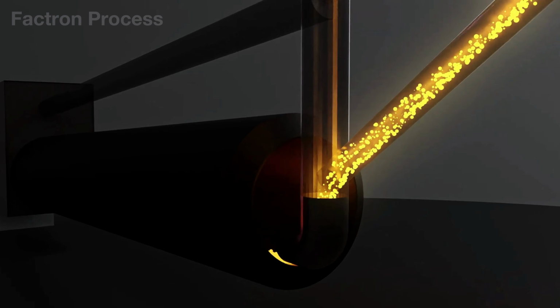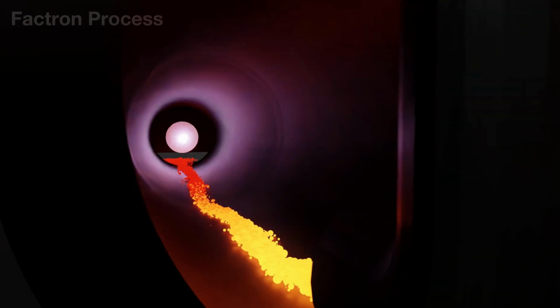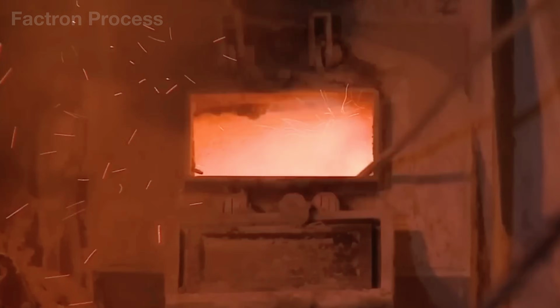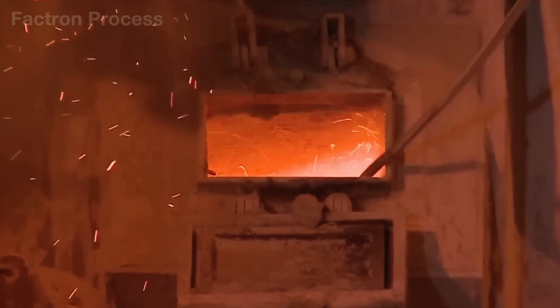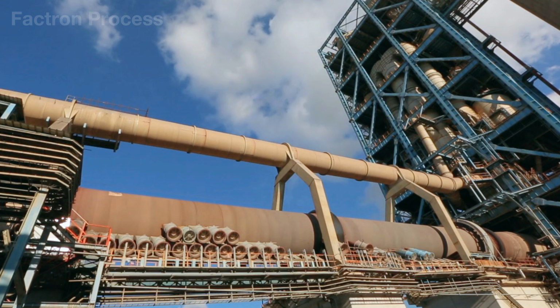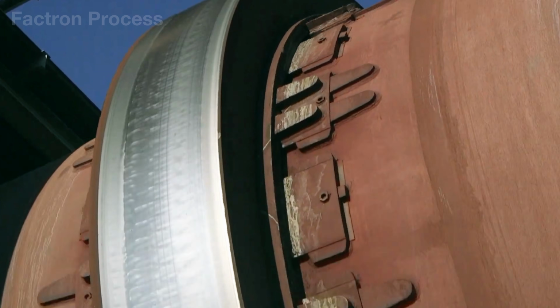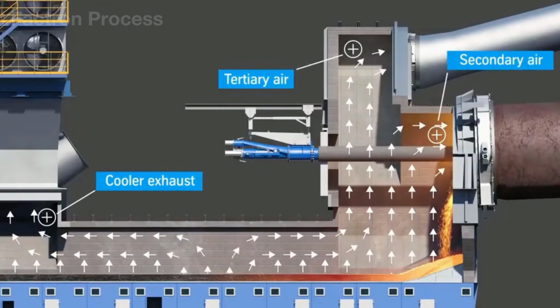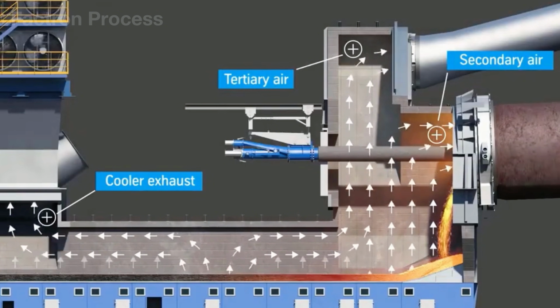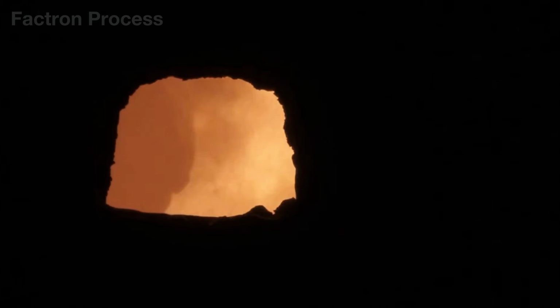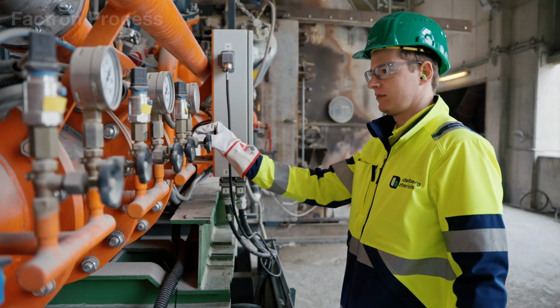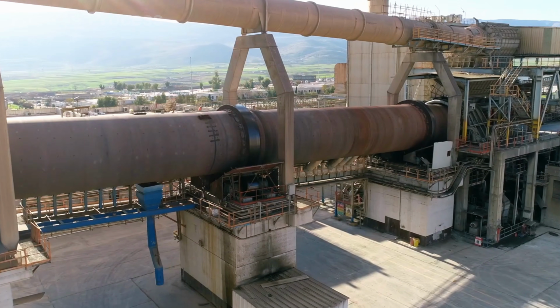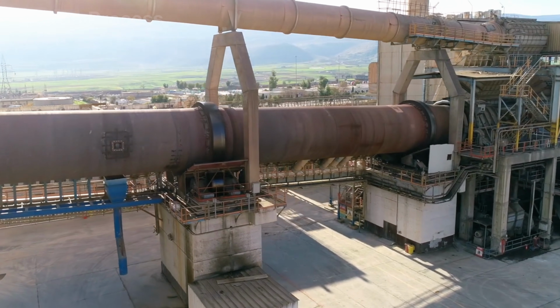At these temperatures, the raw meal does not melt completely like metal. Only about 20 to 30% of the material enters a liquid phase, just enough for the various oxides to react, agglomerate, and recrystallize into clinker. Within these glowing red nodules are alite, belite, aluminate, and ferrite, the mineral phases that determine the strength, setting behavior, and binding performance of cement.